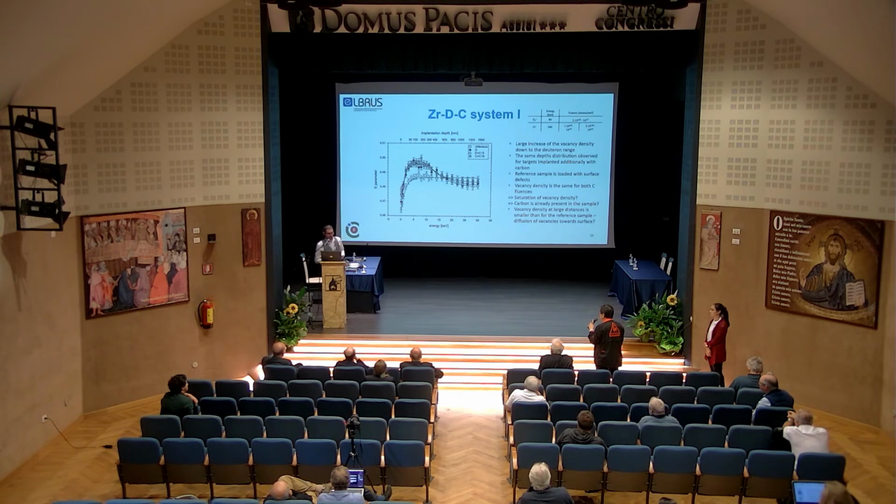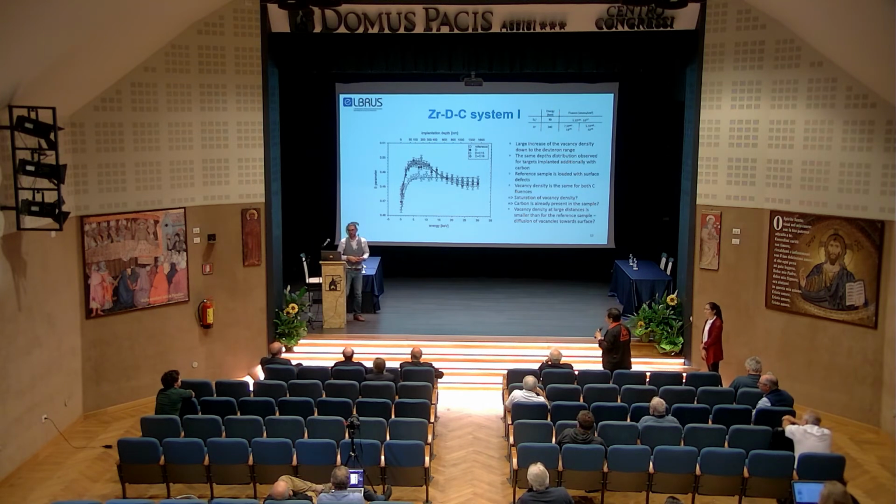For the reference material. Yeah, for the reference material. The reference material is a laminated plate of zirconium. Understand. Lamination doesn't create any vacancies; it just creates dislocations. Okay, I got it. Yeah, cold rolling. Cold lamination. Cold rolled sample mainly. Okay, got it. Thank you very much.